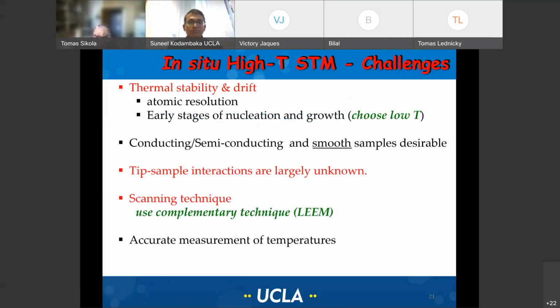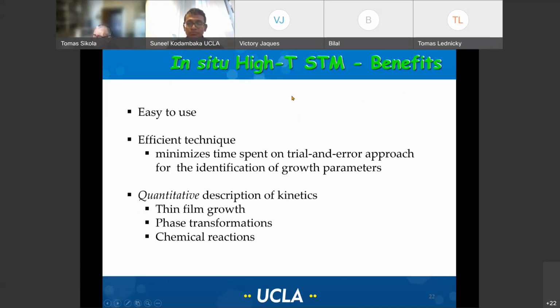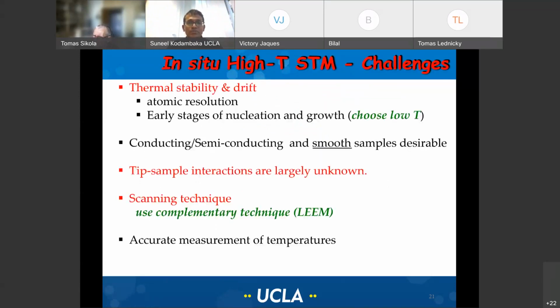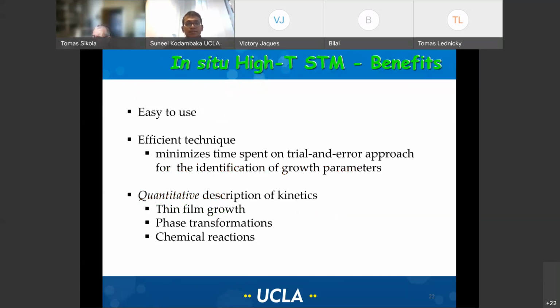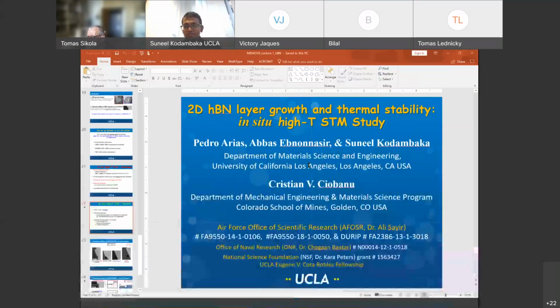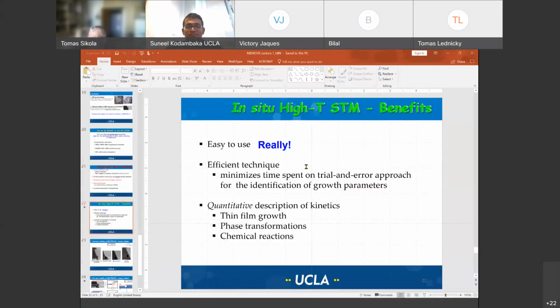Some of the challenges that we commonly encounter when scanning at higher temperatures are thermal stability and thermal drift. And yes, it's inevitable, but you can work around it by choosing lower temperatures or by waiting for longer times. And also, if possible, you can use LEEM. It's fairly easy to use at different temperatures, and the advantage is that you get to observe phenomena in real time. That's the key for extracting quantitative information on different types of phenomena. Okay, with that, I'll stop, and thank you for your attention.